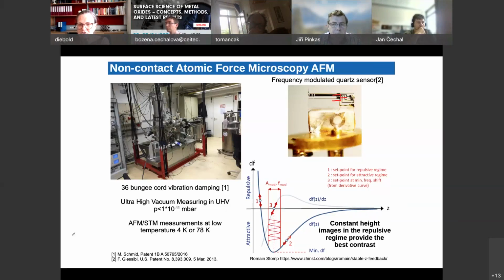And depending, so you bring the tip close to the sample. It has its own resonance frequency. You bring it back, bring it closer, you bring it closer. And this is then, so to speak, the set point. So you put the tip here, it changes, you have a little bit less than the resonance frequency. You change the amplitude. And then the signal that you measure is the change in resonance frequency, the DF.